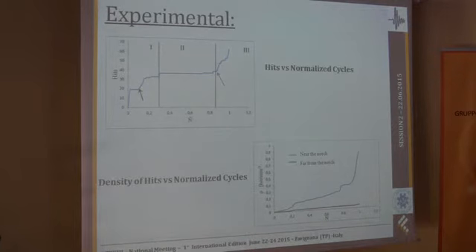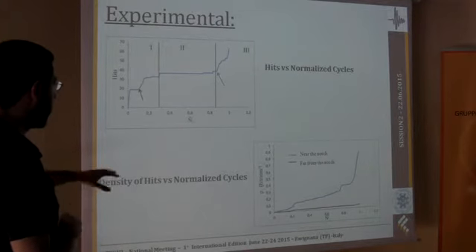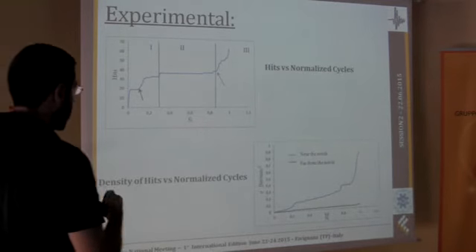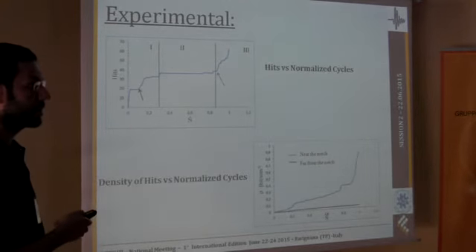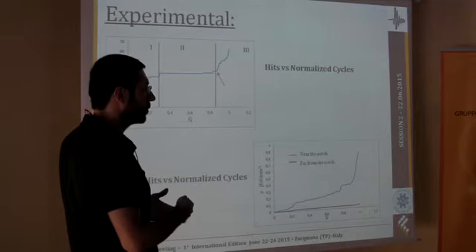It's also interesting to compare what happens in terms of density of hits per volume near the notch and far from the notch. As you can see, if we express in terms of density, you see that most of the acoustic activity observed is observed near the notch. That is to say that the stress concentration area acts in order to promote this kind of dislocation movement, crack initiation and crack propagation.